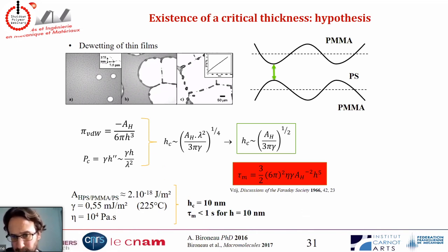So the mechanism basically is that you have some thermal waves at the interface due to thermal energy, for example. And when the layers are thin enough, the initial instability will be amplified by the van der Waals interaction, say, of the PMMA layers that will see each other in between the PS layer. If you put some numbers in that, the critical thickness at which the van der Waals interaction becomes dominant over Laplace pressure will give you typical numbers on the order of 10 nanometers. So it's really similar to what we saw in our multi-layer system.